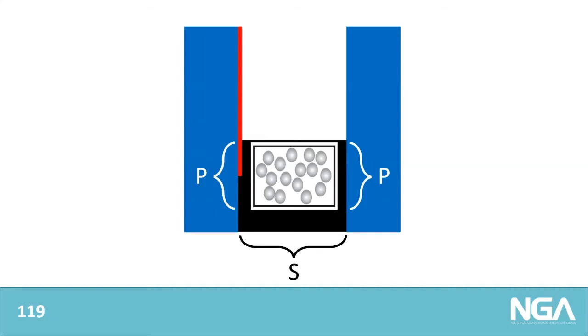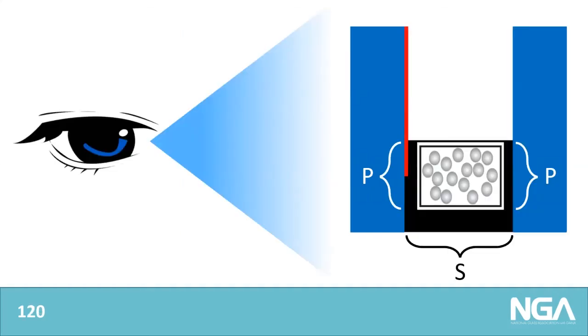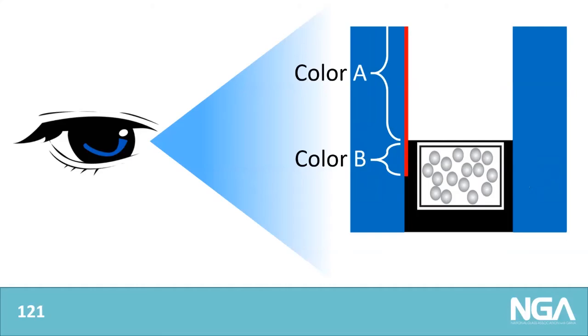Now, if we have a structural silicone glazing application or a structural glazing tape application, in those situations, we don't have metal trim pieces on the outside of the construction. We have only the framing behind the glass. So if you're looking at the glass from the outside, as we see here, you're able to see the termination of the coating above the primary sealant. And the issue is that the color of the coating in the vision area and the color in front of the primary seal could be appreciably different from one another. So we don't want this to be a surprise to the project team. We want this to be evaluated at an early design stage, typically in terms of full-size mock-ups.